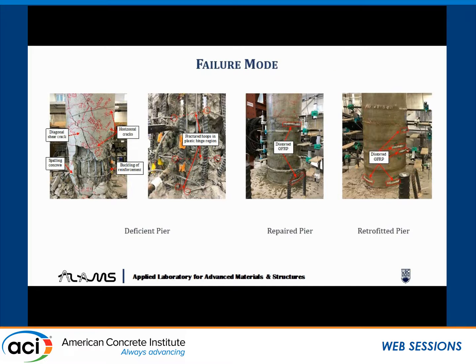And this is the failure mode of the repaired pier and the retrofitted pier. In both cases, under compression, they were showing some sort of distorted GFRP. As you know, under compression, FRP is not that strong. And in the repaired pier, there was a little bit of fracture at the end, and the reason is that at one point there was a little bit of a sharp edge from when we did the formwork, so that had a stress concentration. Otherwise it would not have experienced rupture at this point.